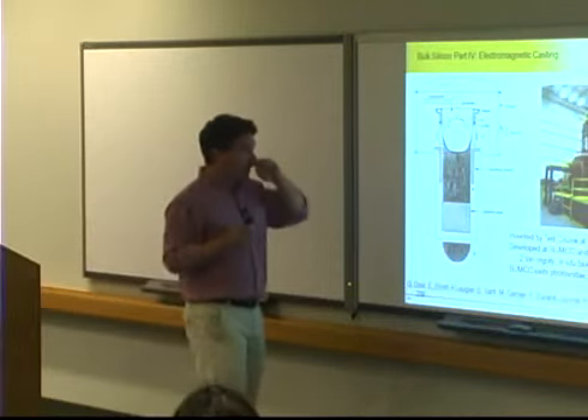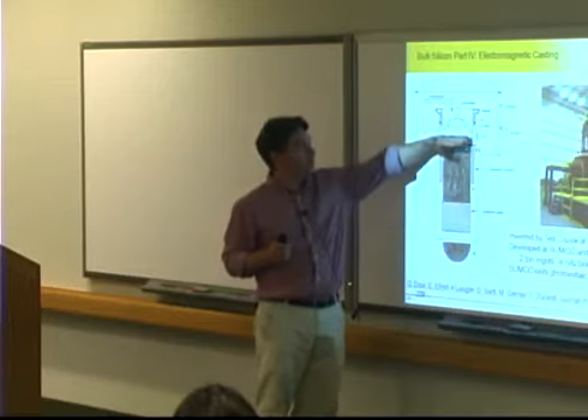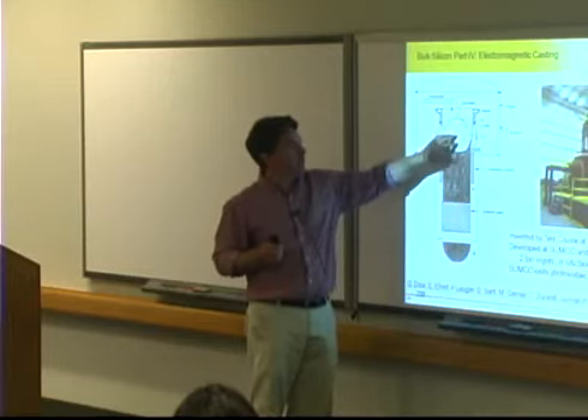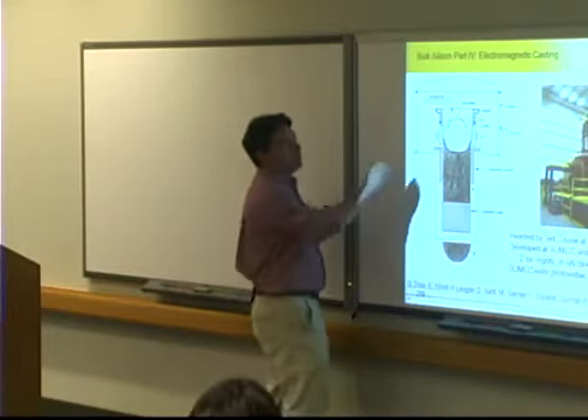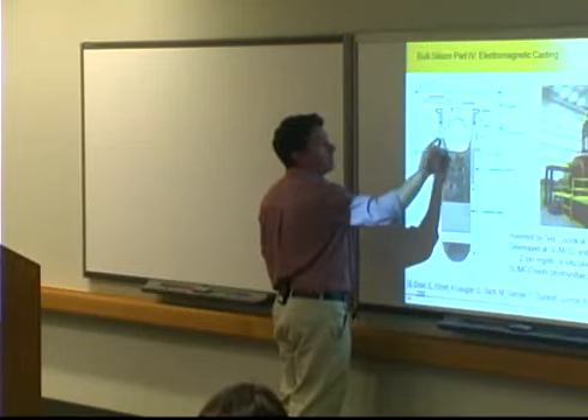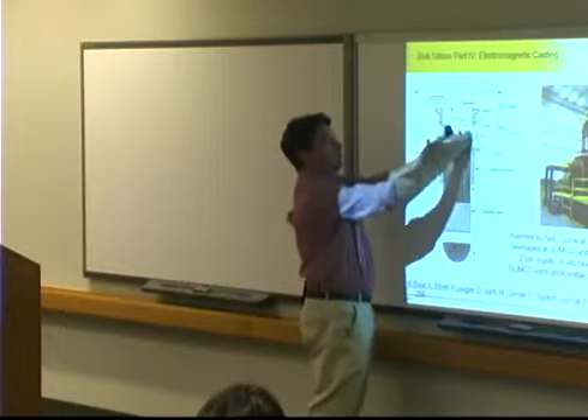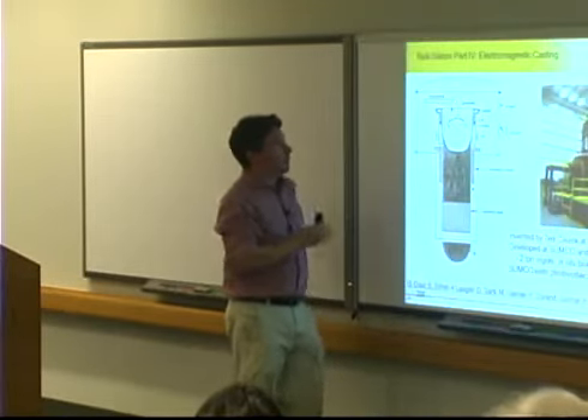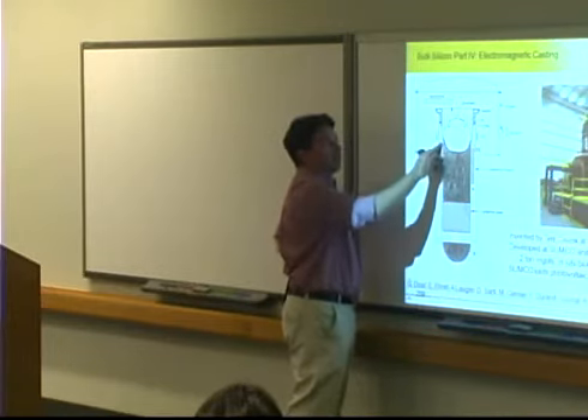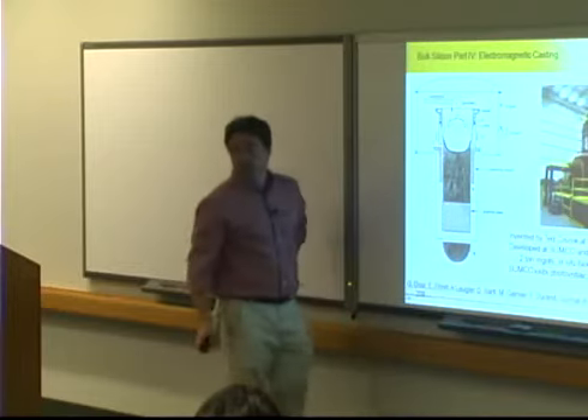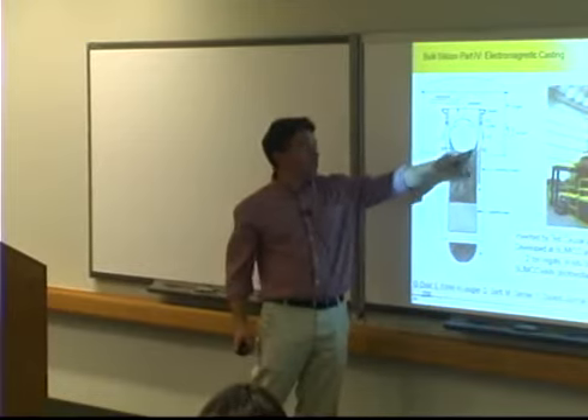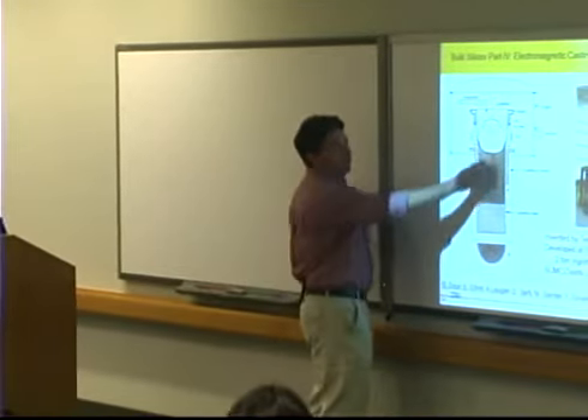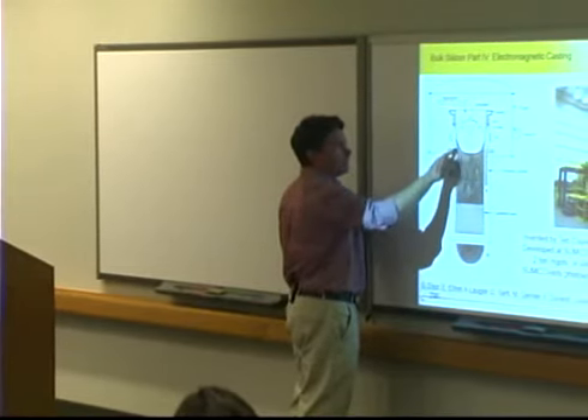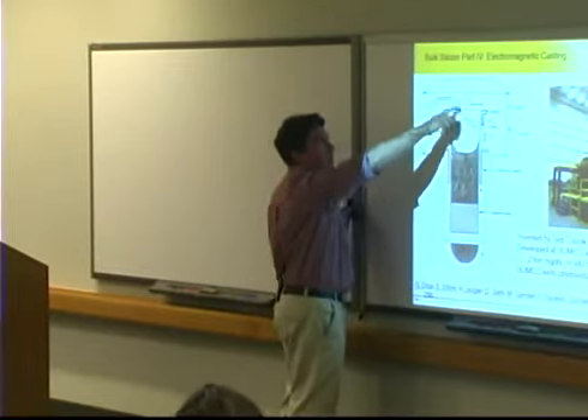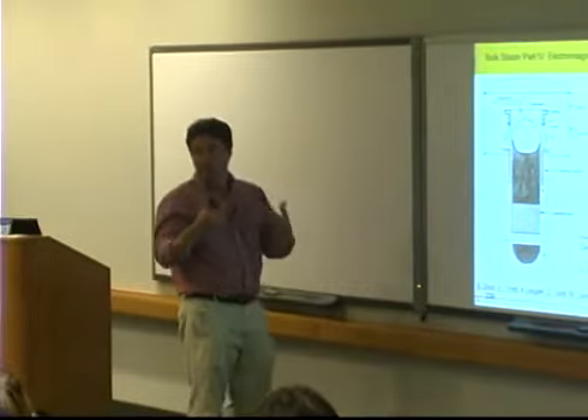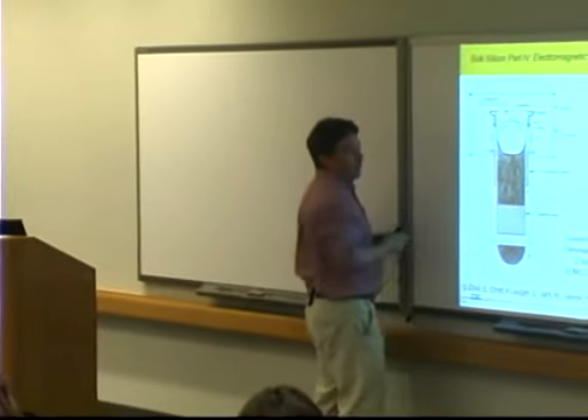And in the center of this square cavity, they start out with a graphite base that's more or less all the way up here. They melt the silicon that they put in here, and because of an electromagnetic repulsion that happens between the current that's running in the silicon and the current that's running in the heater, you get this kind of bubble-shaped liquid up here. And because this is water-cooled, it's also aggressively cooling the liquid next to it. And so you get this kind of a liquid-solid interface. So once you start growing this thing, you have this big solid ingot, and you have this cup of melt on top. And so you keep dropping solid granules from the top. They keep melting, and then you keep solidifying as you go down.